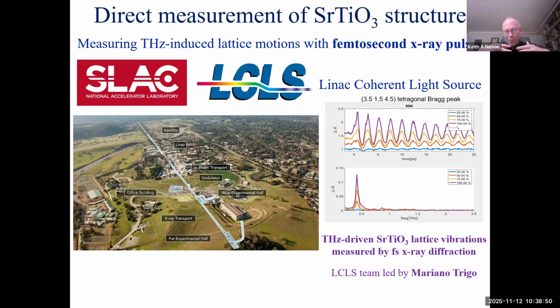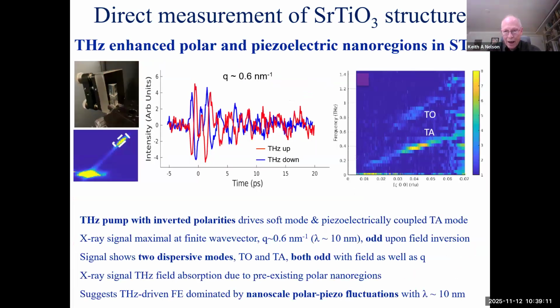And so what happens is we come in with our terahertz field and suddenly we can see all these coupled lattice vibrations going, because we've moved along one dimension, along one lattice coordinate quite far, but others are coupled to it. This lattice vibration isn't the soft mode that we're directly driving with the terahertz field. It's coupled to it, so its oscillations also follow the terahertz pulse. And maybe more surprisingly, when we actually looked at essentially the soft mode type vibrations, we certainly saw that oscillation, but in fact, it's not at a Bragg peak, it's off Bragg. And that's really quite striking.